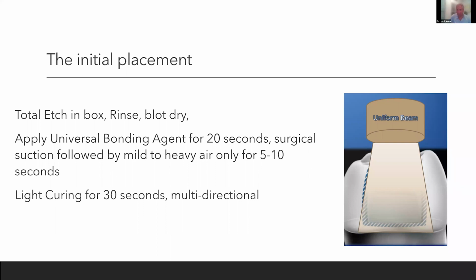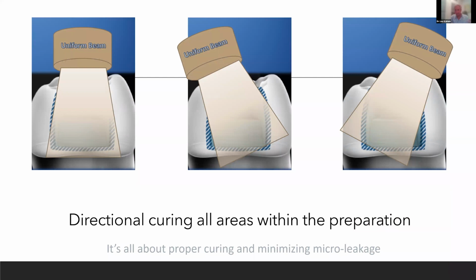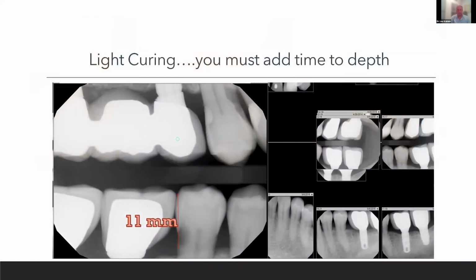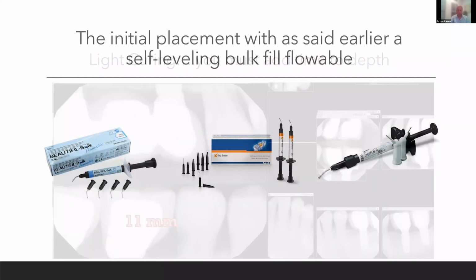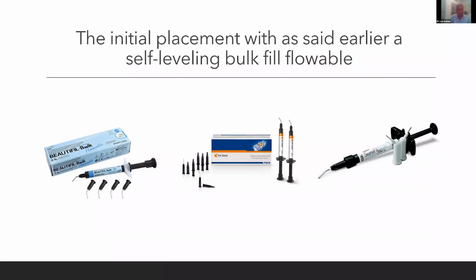You could be 10 or 11 millimeters away. The further the distance, the longer you light cure. When you put the matrix band on, your light is on top of the matrix band. So this is why you've got to cure multi-directional for 30 seconds. Don't be stingy on time. Same thing. I'm going to place the same flowable, one of the 3, in the bottom of the box and